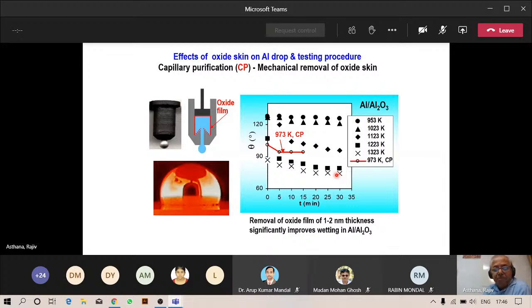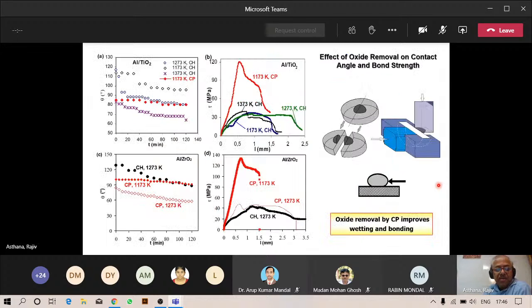We did some bond strength measurements for studying the effect of wettability on adhesion. So we looked at aluminum titania and also aluminum zirconia system. These are the wetting data, contact angle versus time at different temperatures for these two ceramics. And these are the corresponding bond strength data. So aluminum titania and aluminum zirconia after wetting test at these different temperatures. This is how we measured the bond strength.